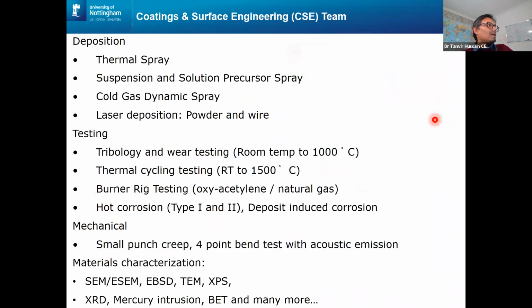In Nottingham, in the coatings and surface team, we work with thermal spray, suspension, and cold spray. We also have got a couple of lasers. We do testing in tribology and wear, from room temperature all the way to 1000 degrees Celsius. We do thermal cyclic testing, burner rig testing, and also hot corrosion, which is a deposit-induced corrosion, for type 1 and type 2. Mechanical systems are geared for testing these coatings under creep, under fatigue, or 4-point bend testing. And we have the standard characterization equipment with electron microscopy and other types of spectroscopy.